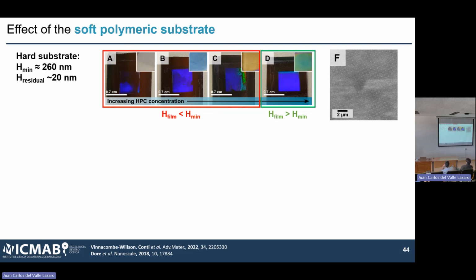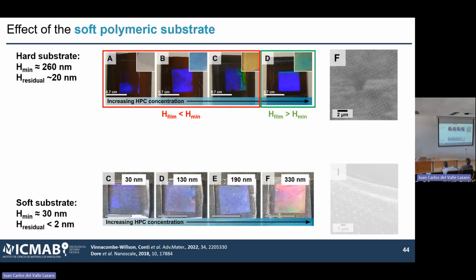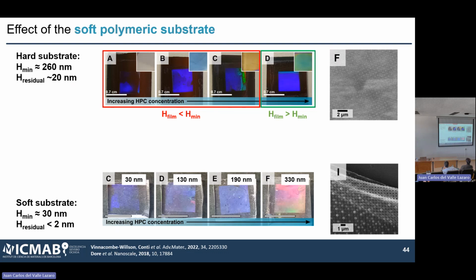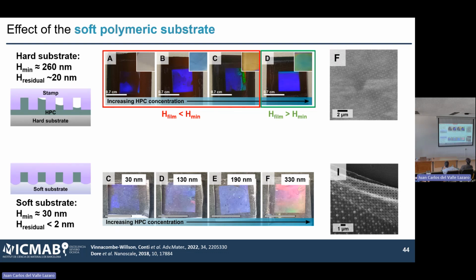Because if you do this on a silicon substrate, you will never be able to make something so thin. When you use a stamp and you press to deform your HPC, the cellulose needs to fill up the stamp. And if you don't have enough material to fill up the stamp, it will be filled unevenly. So you will have areas where the HPC goes up and other areas where it doesn't, and your fishnet will turn out like this. So very bad. But that's why we used a PDMS substrate, which is a soft substrate. And so we were able to go as thin as 30 nanometers, as confirmed here by this TEM. So the idea we have in mind is that when you have a soft substrate, you can press very, very hard and basically convince your HPC, your cellulose, to fill your gaps in an even way.